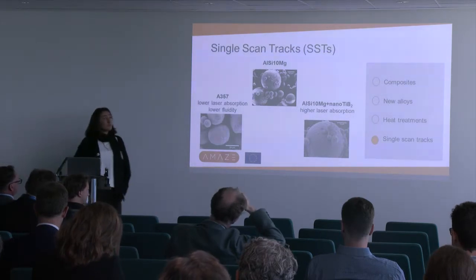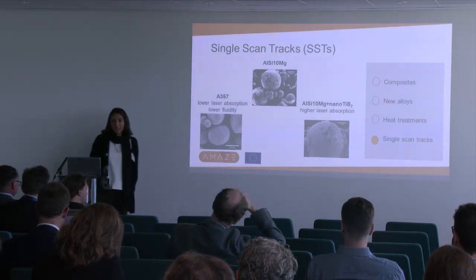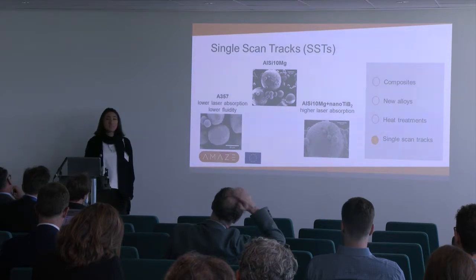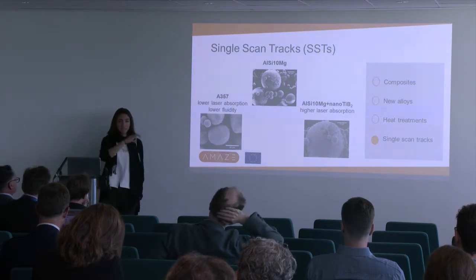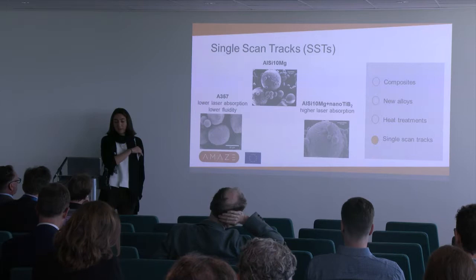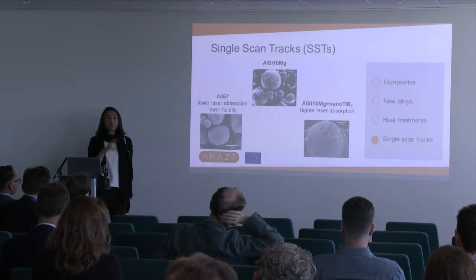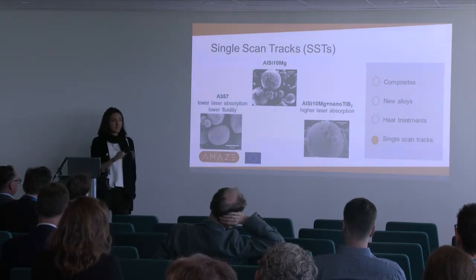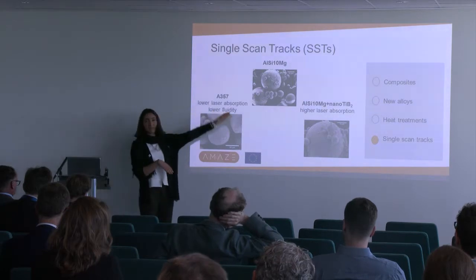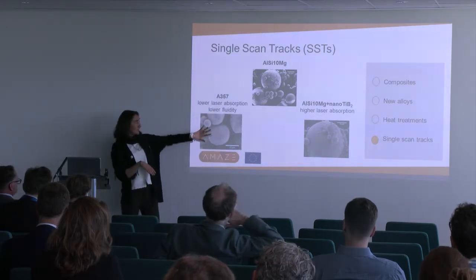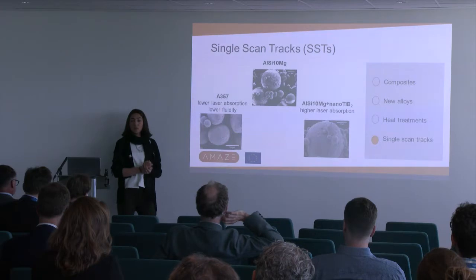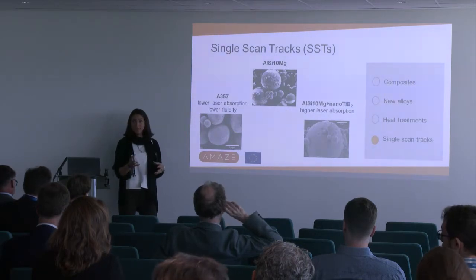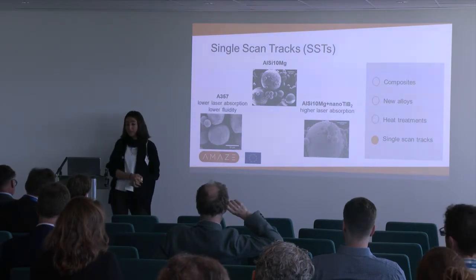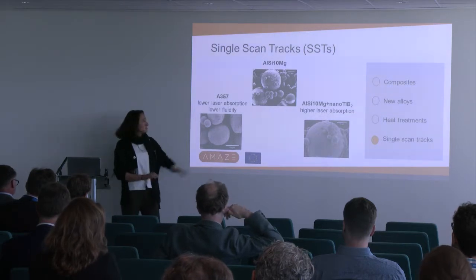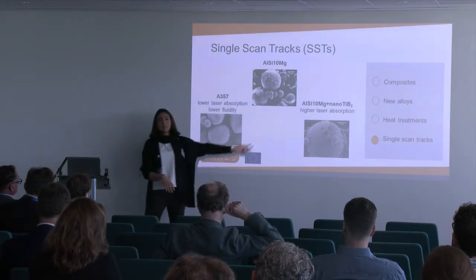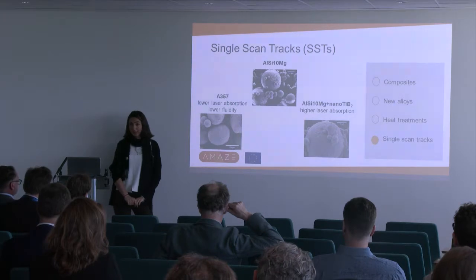So then I will move, as I said, to the single scan track analysis. We did some single scan tracks. The scan was just doing a line on a powder bed, and we chose three aluminum-based materials. We have the classical aluminum silicon 10 magnesium, the A357, which contains lower silicon content, so 7% instead of 10, and the composite, which contains 1% nano titanium diboride particles.